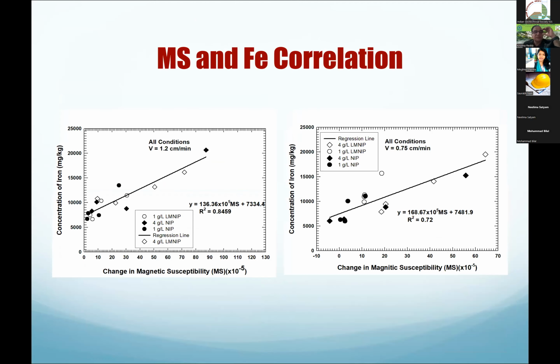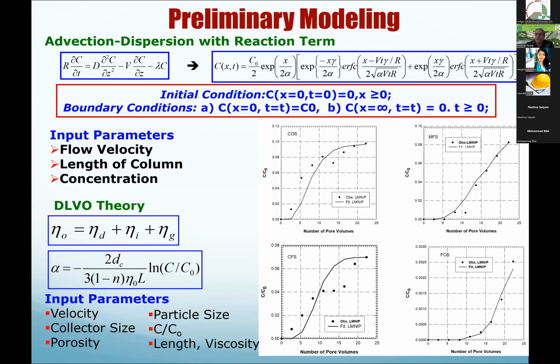And then actually there is a correlation between magnetic susceptibility reading and iron. So you don't really have to measure the iron concentrations. If you can measure the magnetic susceptibility just by exposing the sample under the sensor, you can read that reading, and then that has a good correlation to the iron content.